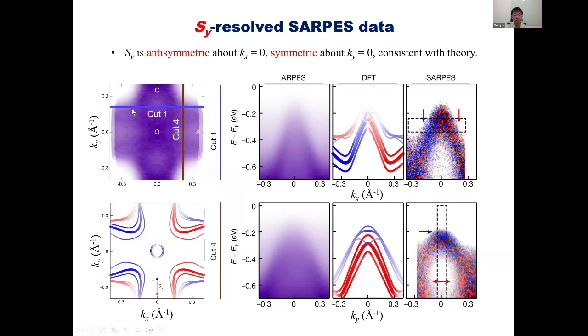So we continue to do cuts along 1 and 4 here. According to our DFT calculation, it has this type of red and blue texture. For some reason, we can see this band instead of this band; this band is not seen in our data. I don't know why, but it's probably a matrix element effect. Here we can see that the blue comes to the top and the red comes to the bottom, which is still consistent with our calculation.